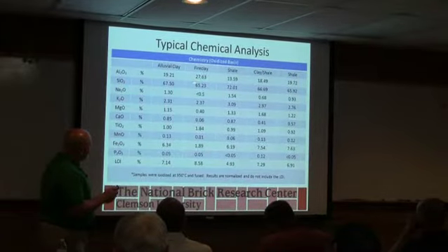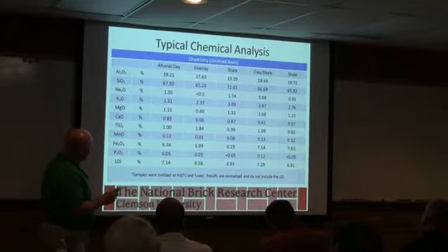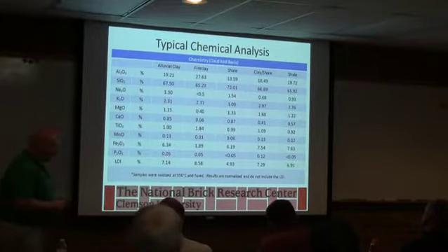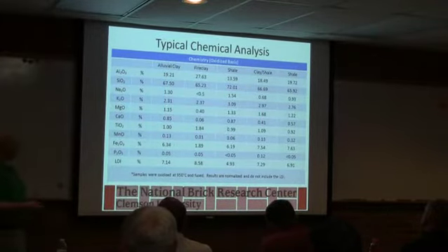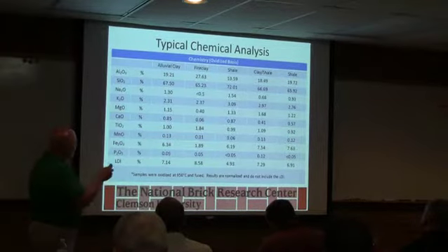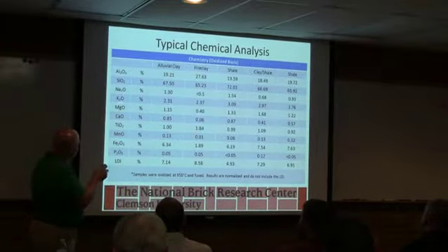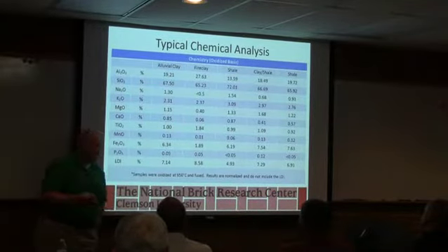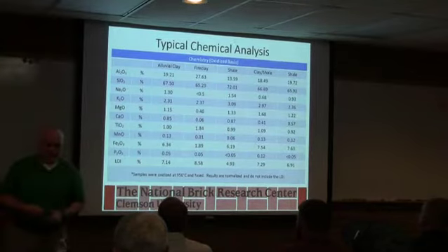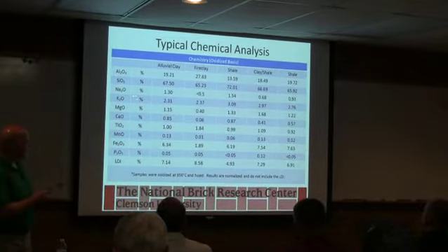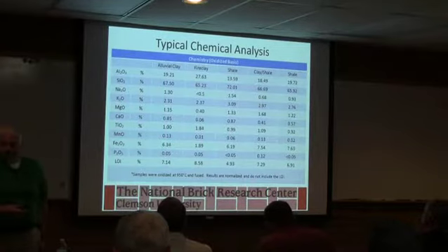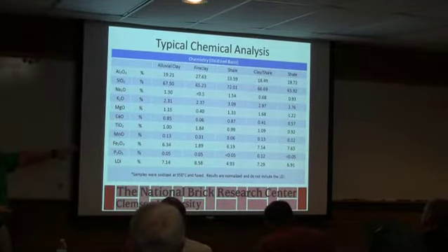If you see a good number here, something in the high 20s, you can expect a reasonably plastic material. This guy right here, I wouldn't expect to be terribly plastic at all, okay? Because it's just what the analysis tells us. These guys in here, especially the sodium and potassium, they're the fluxes, okay? That's what helps lower the firing temperature. The more of those guys you see, usually the lower your firing temperature is going to be. So you can kind of look at this and get an estimate of where the firing temperature is going to be on it.